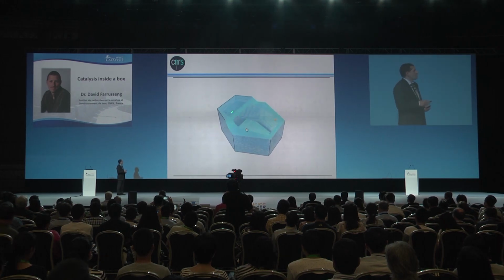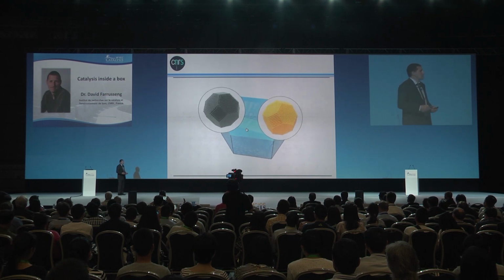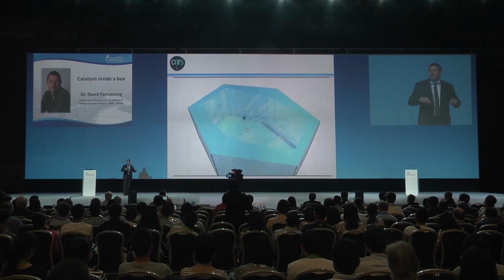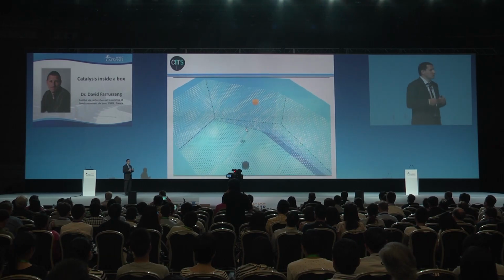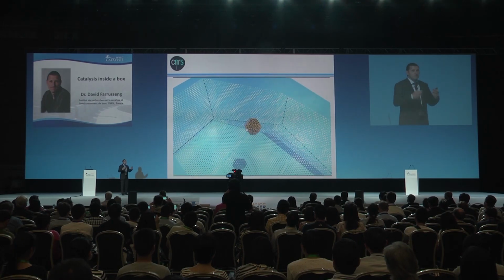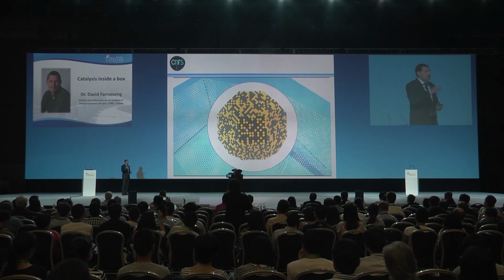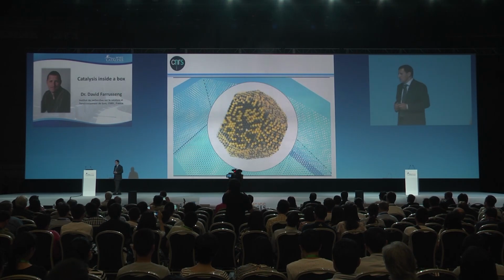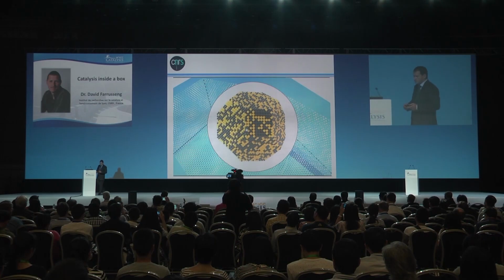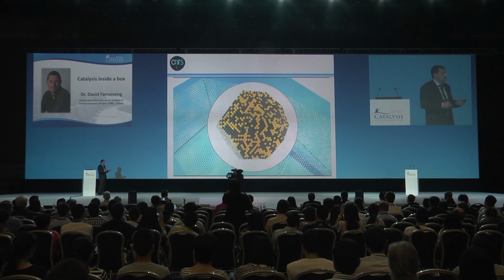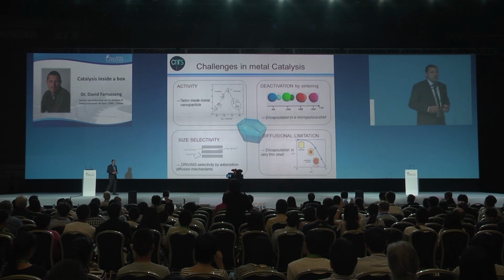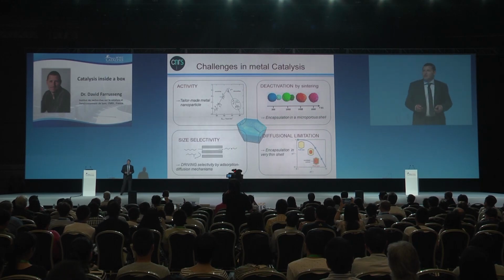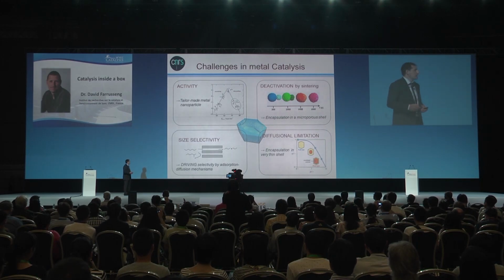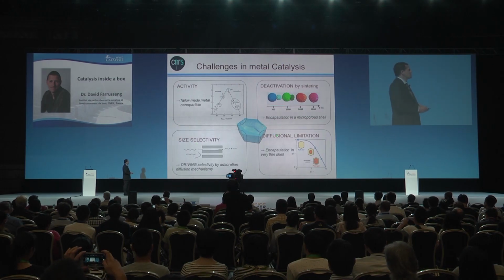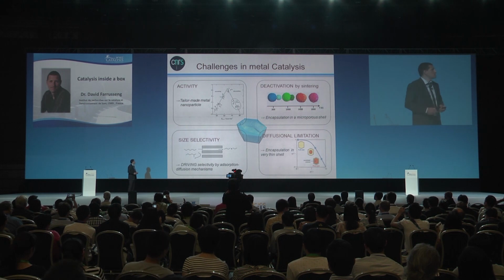So you have a huge cavity, and inside we're gonna put metals, and eventually these metal particles will collide and form a unique single particle encapsulated in this zeolite membrane. And with this new system in hand, I'm gonna revisit key aspects in catalysis, so 4 different aspects: activity, deactivation, size selectivity, and diffusional limitations.